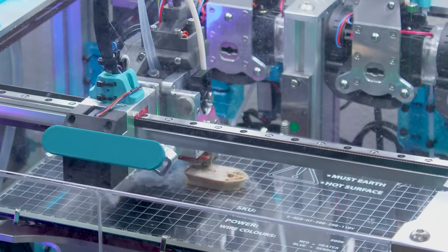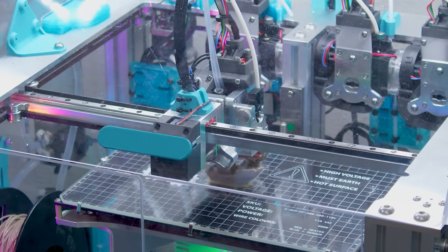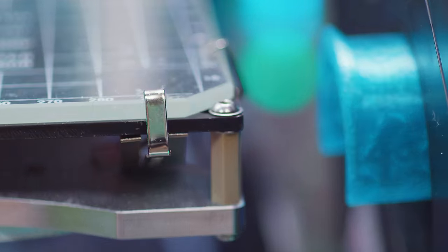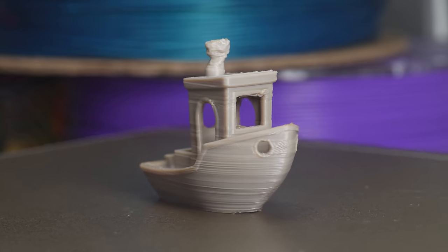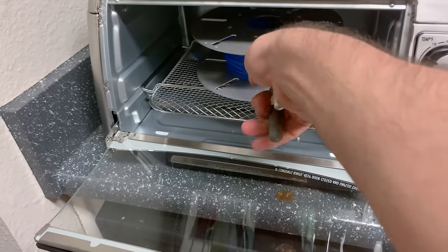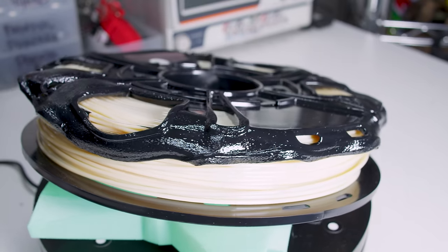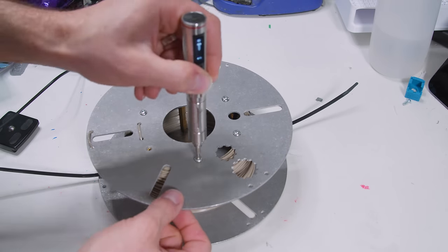Harnessing this power is not easy. This material, like many of these other superpolymers, prints at 400°C, a full 150 degrees above my Prusa Mk3S's safe operating temperature. You're going to need a 140-degree bed and a 100-degree heated chamber, and the nozzle is over 80 degrees hotter than a soldering iron. This is a $9 Benchy because PEEK costs $600 USD per kilo. To dry this filament, you have to bring it to 120°C — a full 50°C hotter than a food dehydrator. That is zesty enough to melt polycarbonate, which means you'll need to transfer the filament to a metal spool, or the spool itself will melt.